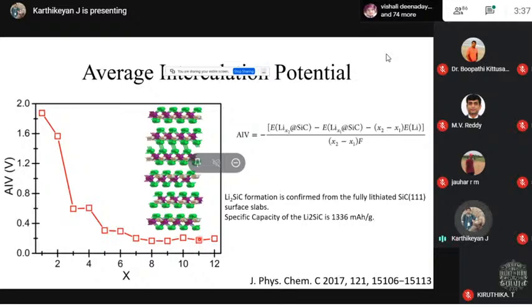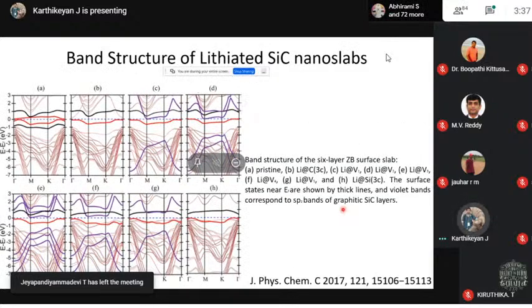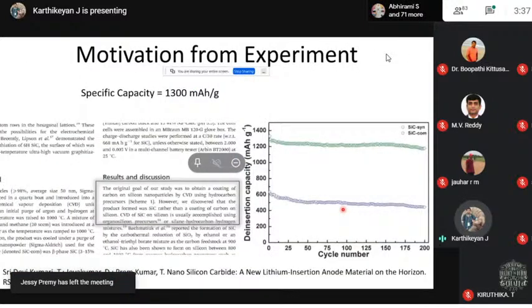And also we have calculated the specific capacity for Li2SiC. For this composition, it comes to be 1300 milliampere hour per gram. That is what experimentalists have observed. They have obtained this capacity for nano silicon carbide. They tested it for commercially available silicon carbide particles also, because that was larger in size.